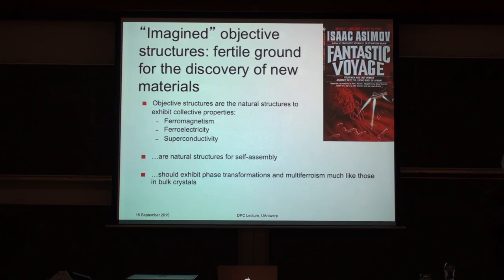If you have a material that you just cycle back and forth through the phase transformation, and the temperature at which you transform on heating is the same as the one on cooling, say, then you won't get any work, you won't get any electricity out of this stuff. The thermodynamics requires, if you look at the temperature-entropy diagram, a different transformation temperature on heating than on cooling. And you do that by actually having an applied field. So the applied field plays a very important role.